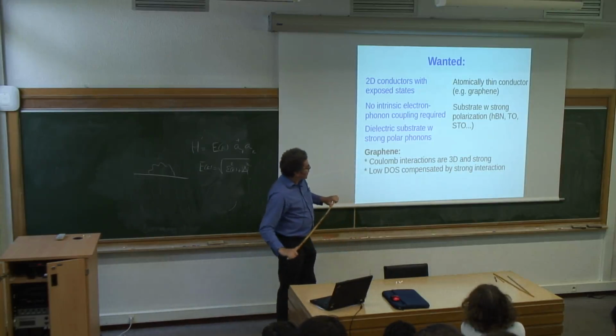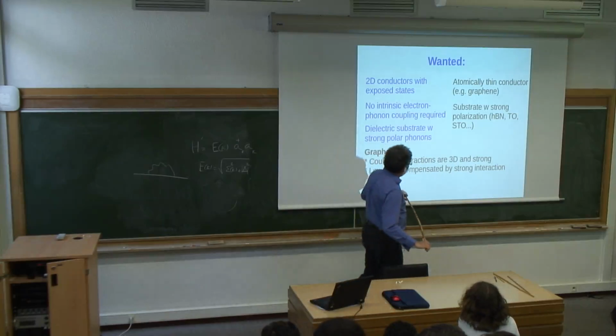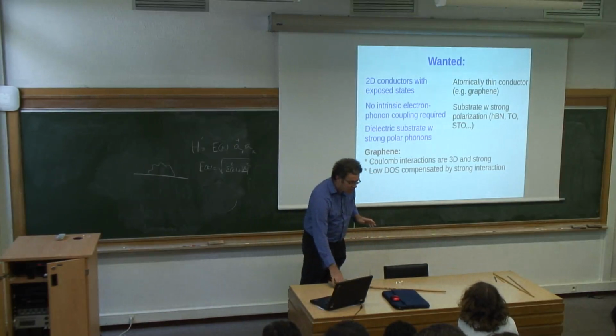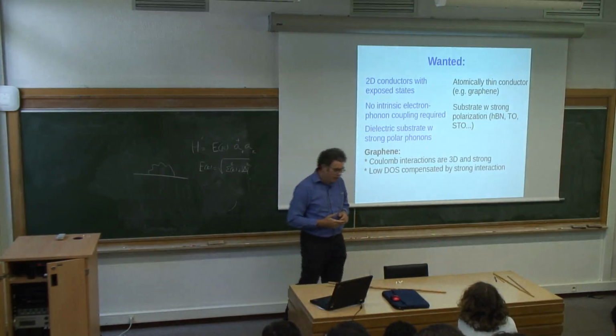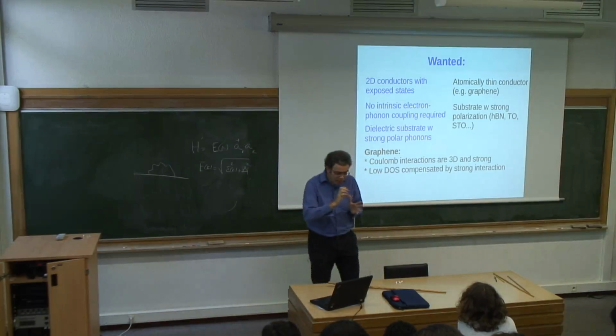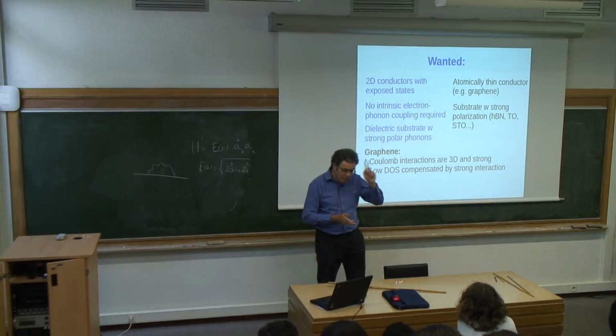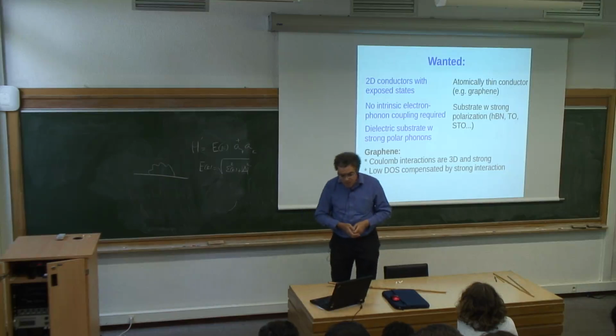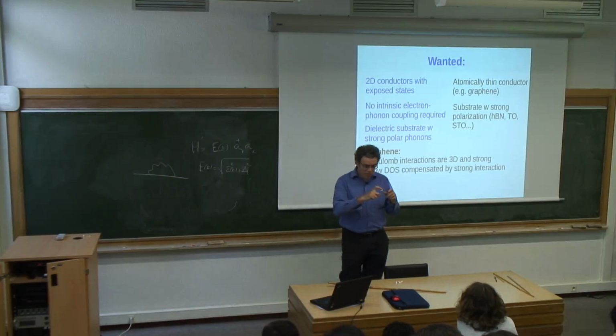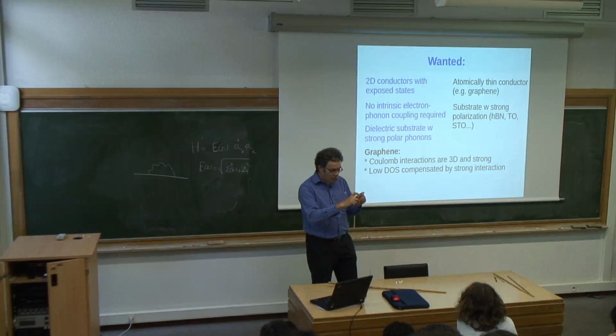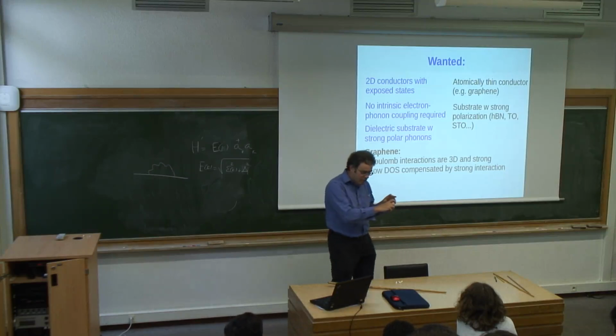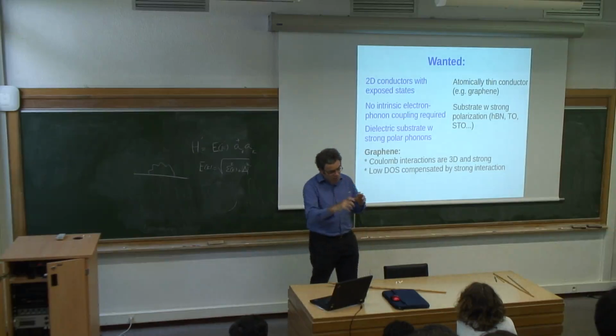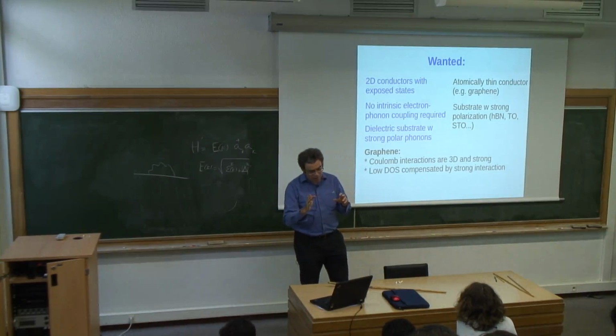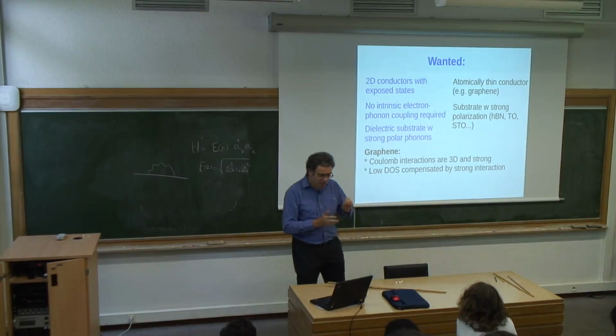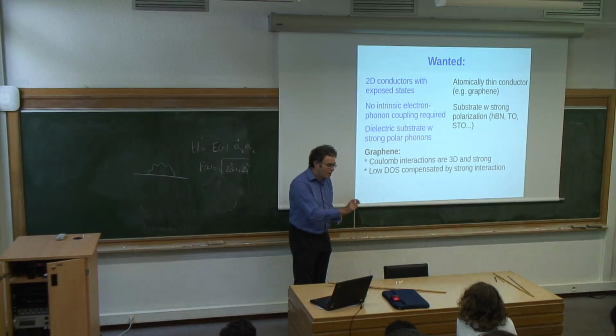Graphene is good because Coulomb interactions are three-dimensional, as we discussed, and they are strong. And also one might argue that in graphene, if you are near the Dirac point, even if you dope it slightly away from the Dirac point, you have a density of states which is small because it's proportional to your gate voltage somehow. And the density of states appears in the exponent, in the BCS exponent. So you would say that because the density of states is small, it will be exponentially suppressed. However, interestingly, the Coulomb interaction varies proportionally. So the Coulomb interaction strength, which is reduced by screening, becomes unscreened as you approach the Dirac point, and it becomes unscreened in such a way that the product of interaction and density of states basically doesn't depend on doping. It doesn't depend on carrier density unless you go really, really close to the Dirac point, at the scale below KT.